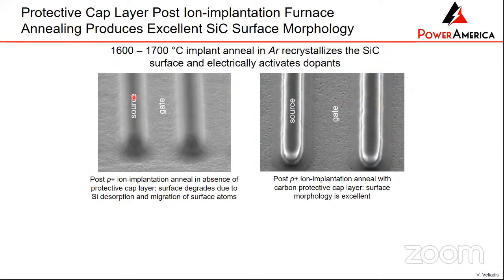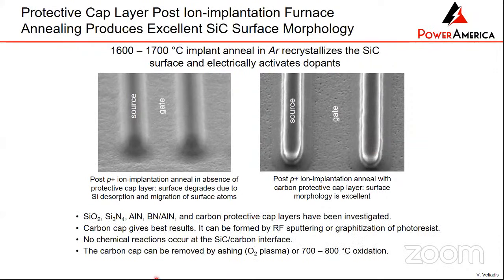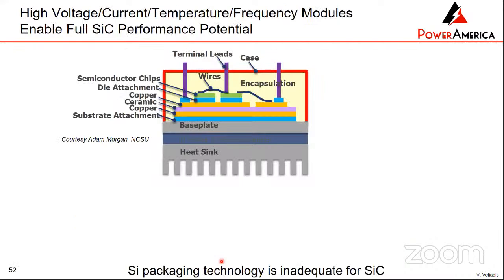This was a wafer where no protective layer was put on top when we went to that 1600 degree anneal. And this is a wafer that did have a protective layer. Obviously, none of the devices on this wafer worked. And you can see how nice and clean it looks after the anneal when you use the correct protective layer. There are several options for protective layers, and this is part of the technology you develop in order to process a new type of material in a foundry. Okay, and the last thing that I wanted to talk about is the module and the package.